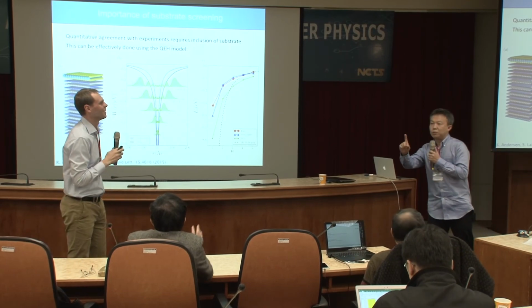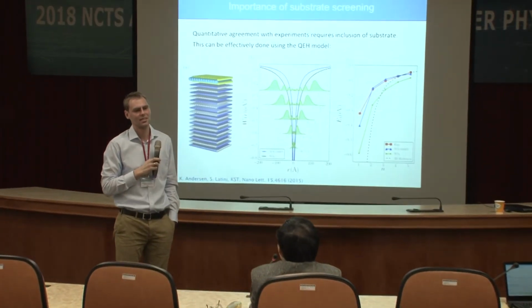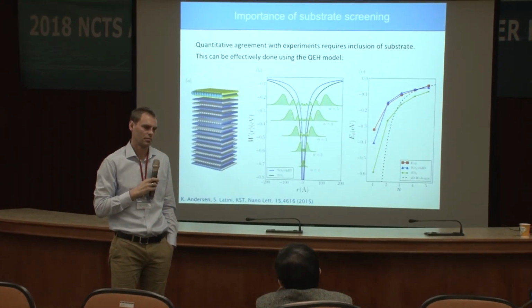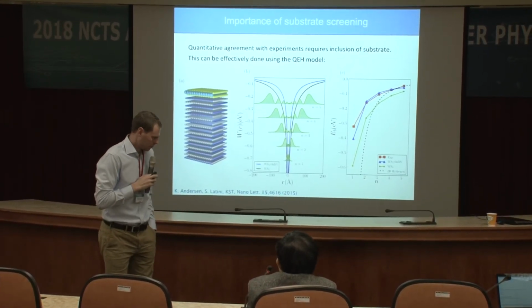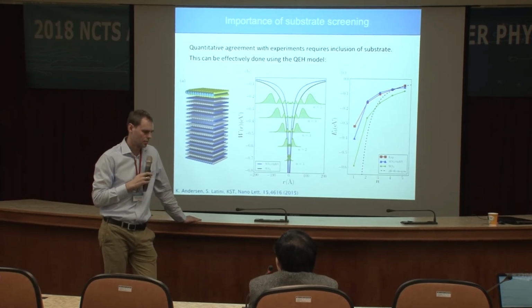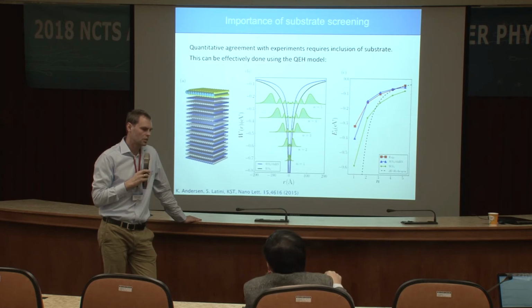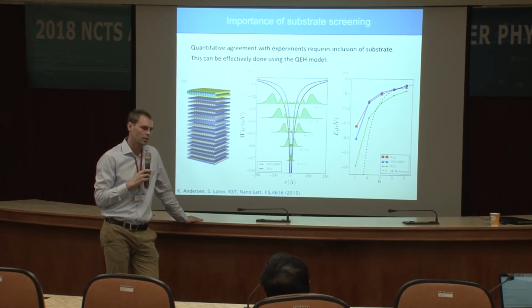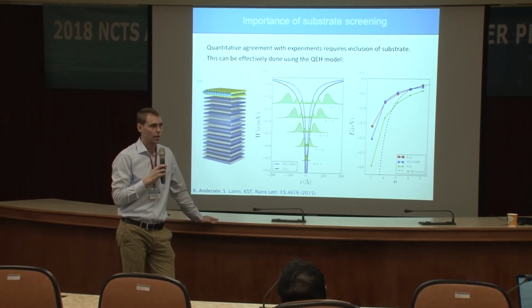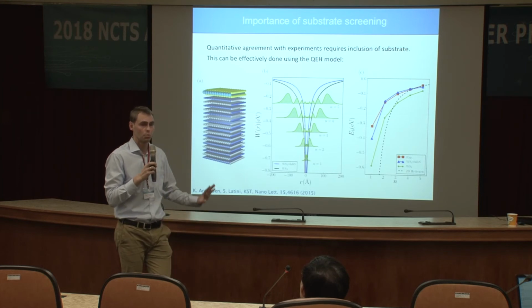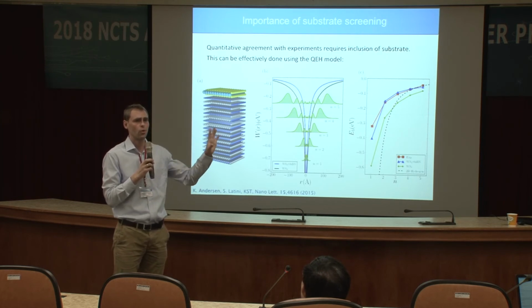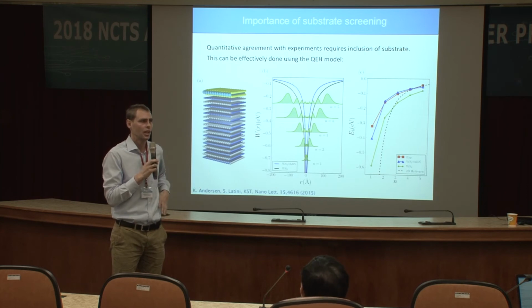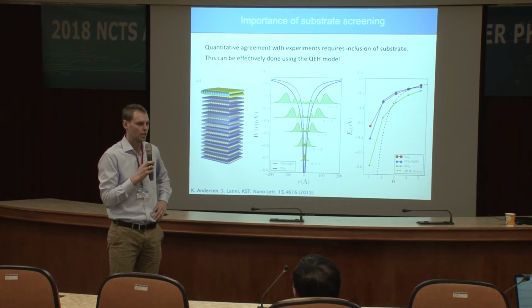Okay. Okay, we have one more question, please. Yes. Very impressive. I have a simple practical question. Near the end of your talk, you show an example of, I don't know which material. So my question is, what kind of computing facility did you use for the calculation and how long does it take? The BSE calculation with 48 by 48 k-points? Yes. So we use here a plane wave cutoff for the local field effects, the G and G prime vectors, of 100 eV, if I'm not mistaken, or 80. And then we included 4 conduction bands and 4 valence bands. And this takes around a day on probably something like 100 cores.